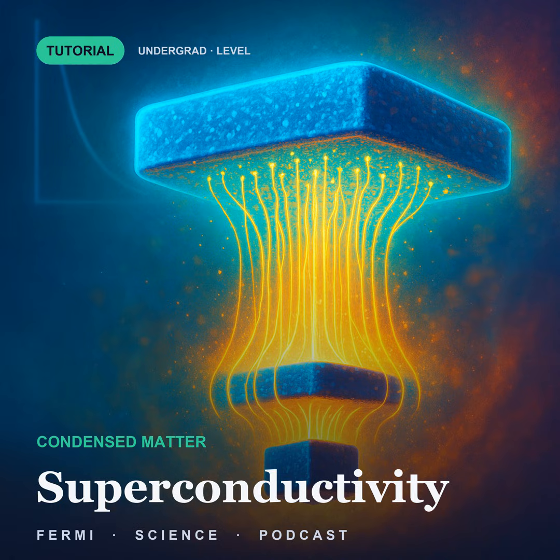Two things fall out of that before I ask for them, and I want to check both. The prefactor is the phonon energy, and the exponent contains only the coupling, nothing about the ions. A phonon energy goes as 1 over the square root of the ionic mass, so the transition temperature must too, with an exponent of exactly 1/2, which is the isotope measurement, predicted rather than accommodated. Predicted rather than accommodated, and it was the strongest early evidence there was.